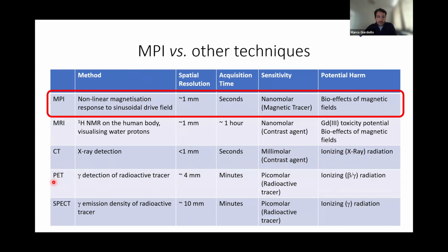And then obviously, just very quickly to mention other techniques, positron emission tomography and SPECT use gamma radiation. Resolution's still pretty good. They take minutes, but obviously you're using ionizing radiation. So MPI has its advantages against other techniques in terms of limited harm. You're directly looking at the tracer, and you can quantify that tracer. I suppose it has the limitation that you will always have to use a second technique to accompany it for anatomical information. And you're limited at the moment to only preclinical.